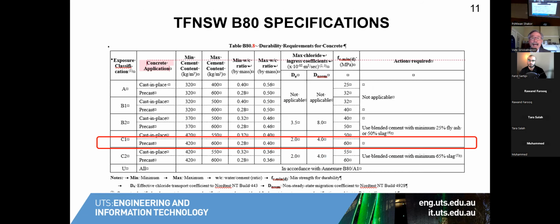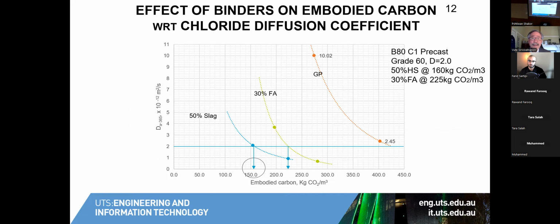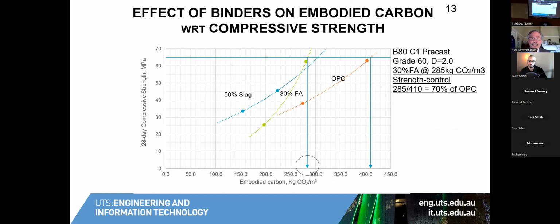Okay. I have another example, but I won't repeat it. In this example, the only thing is that the type of binder that meets the diffusion requirement and that meets the strength requirement are different. Okay, and at the end, in this case, a 30% fly ash would be the best concrete to use for lowest embodied carbon. So you need to understand the behavior of concrete very, very well to then be able to select a concrete with the lowest embodied carbon that meets both the strength and durability requirement.